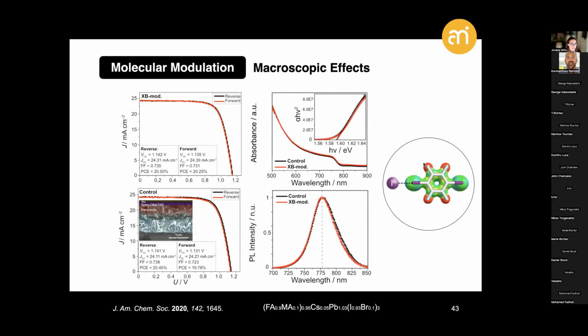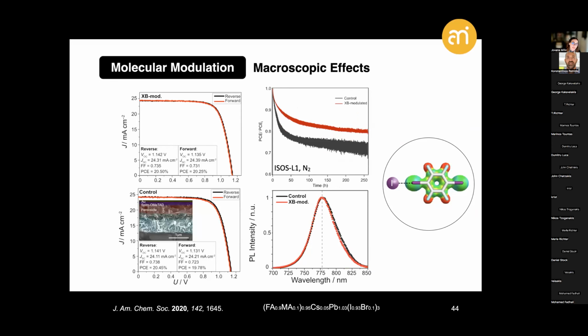However, what we do see consistently is that despite these results in terms of no major effect on the photovoltaic performances, the stabilities of these materials are consistently enhanced, and illustrated here by one of the examples, monitoring the continuous operation of these solar cells by continuous irradiation, enhancement of the stability of the treated sample as compared to the control systems, that was ascribed to both the hydrophobicity of these materials as well as the ion binding capacity related to the intrinsic stabilization.